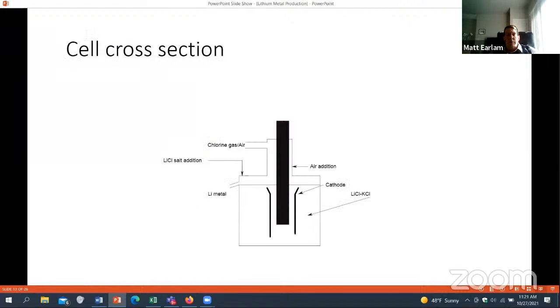And the first of which is to look at the gap. When I say gap, I'm talking about the distance between the anode and the cathode. And you have to remember these are both round. The cathode is round and the anode is round. And so as you get further out, the resistance goes up differently. It goes up as a logarithmic function instead of just a straight function because these two surfaces are round. You also have chlorine evolved here on the anode as a gas, and so it's coming off and out. And then metal is evolved on these plates, comes up and is swept out either this way or into another pool over here where it can be harvested.